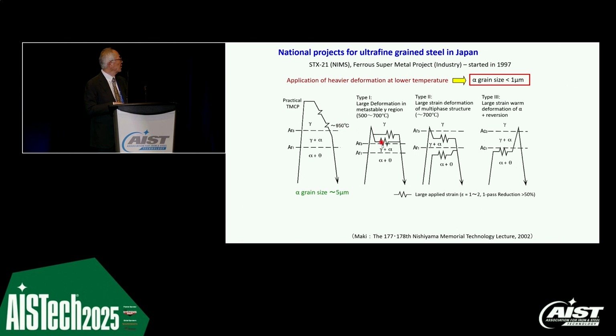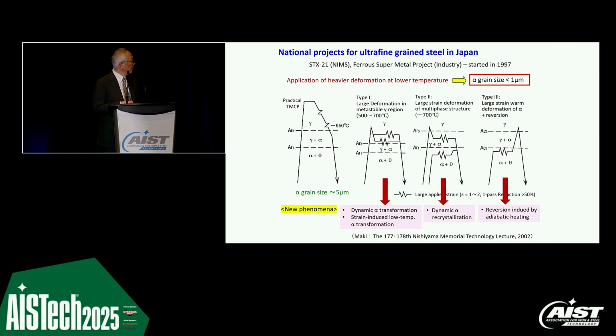And with various heat treatments and thermal processing explored, we obtained ferrite grain size less than 1 micron. So this is normal TMCP, and 5 microns is the target for practical use. And by applying a lower deformation temperature in the metastable austenite field, and also applying a larger strain, then we can get ultrafine grain. And this is the case of deformation applied in the two-phase field, austenite plus ferrite or ferrite plus cementite. And the third one is, again, deformation lower than the A1 temperature, where with adiabatic heating, we can increase the temperature by applying more strain. So interestingly, we found in this project in Japan, new phenomena.